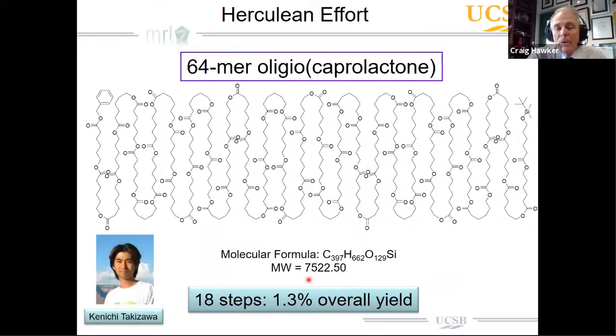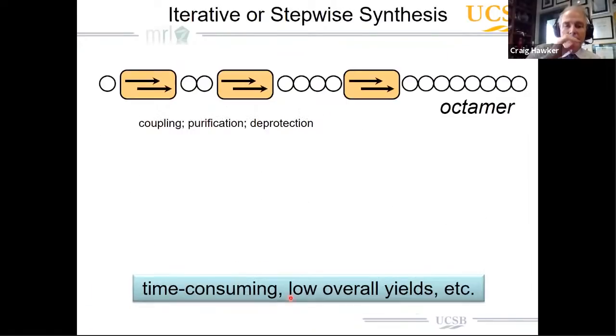The problem was that the overall synthesis of this material was 18 steps with an overall yield of about 1.3%. And so Kenichi was a really hard worker, but it still took him about 6 to 9 months to make a couple of 100 milligrams. And so that was great. We actually learned a lot about the crystalline behavior and the crystal structure of caprolactone from this work, but it still was much more synthesis than we would have liked.